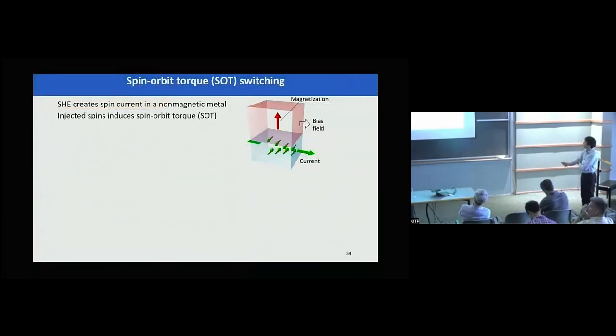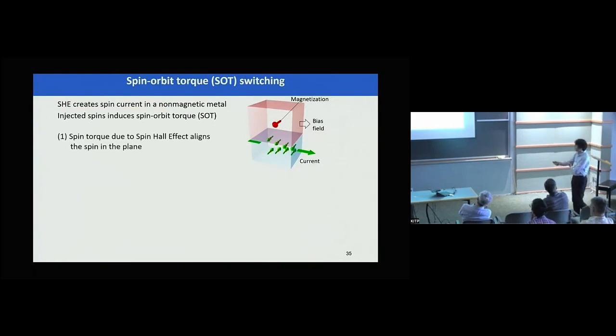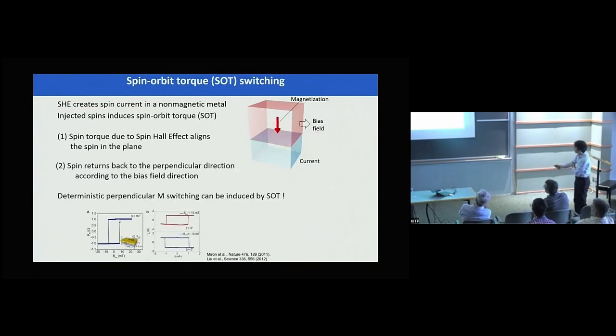Okay, and so then how can we actually develop a small m? This is the way to use spin orbit torque. The spin orbit torque was developed for ferromagnetic spintronics, and you need a heavy metal layer neighboring the ferromagnetic material, which in this case has perpendicularly oriented magnetization. By sending current, you can generate a spin Hall effect, and the spin accumulation at the interface generates this M, and that's actually the spin torque to align the spin in the plane. And if you remove this current, this spin returns back to the perpendicular direction according to the bias field direction. So it's called deterministic perpendicular magnetization switching by the spin orbit torque.